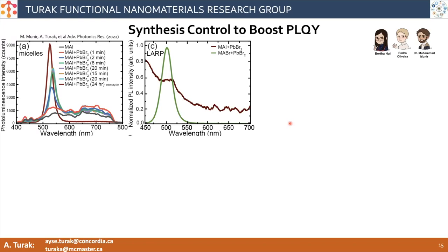So for example, I'm showing here the kinetics of the formation of methyl ammonium lead bromide. Typically, if you're just mixing these in solution, they would tend to form on the order of milliseconds. You can actually slow down that reaction to something like 20 minutes. It's even stable up to 24 hours. And that allows us to produce structures that are not possible using these sorts of precursors with other techniques.